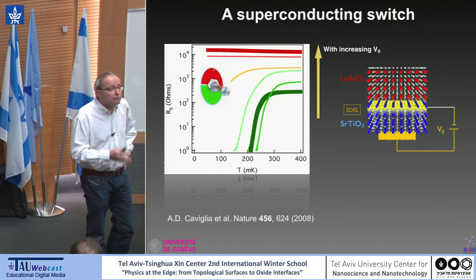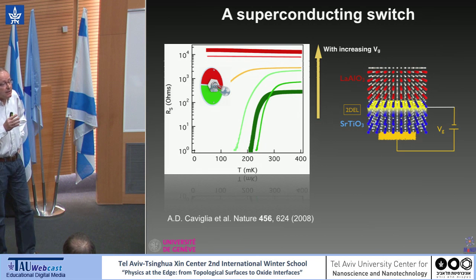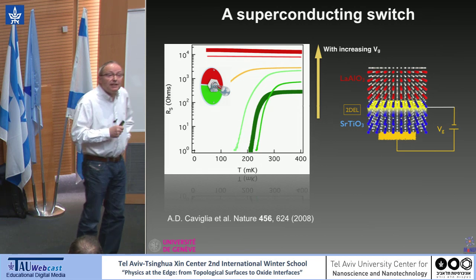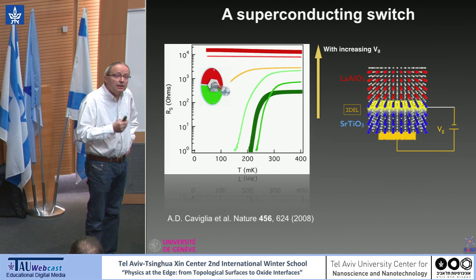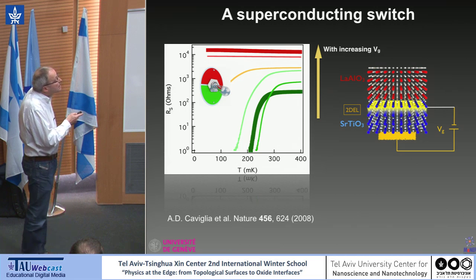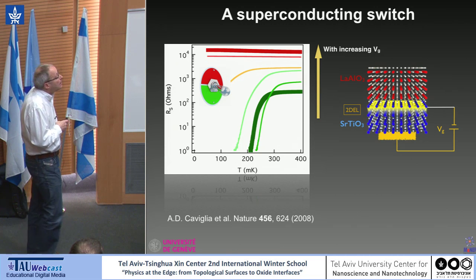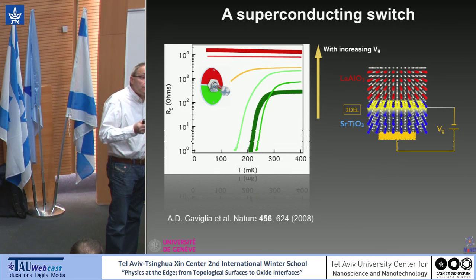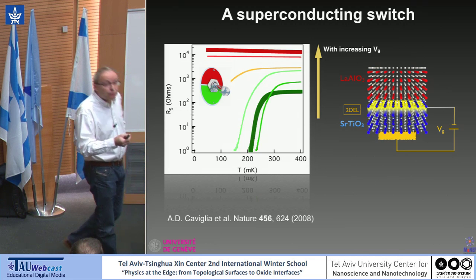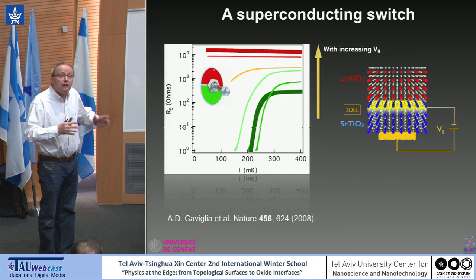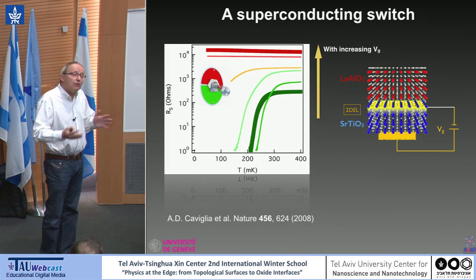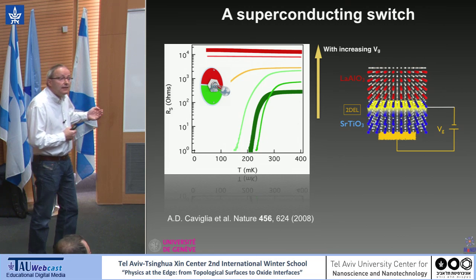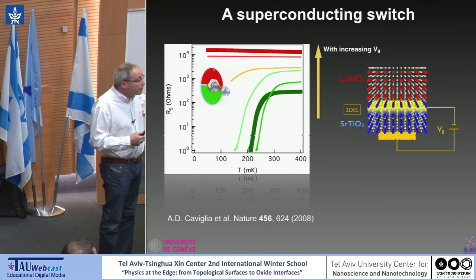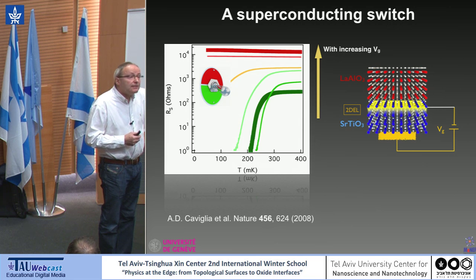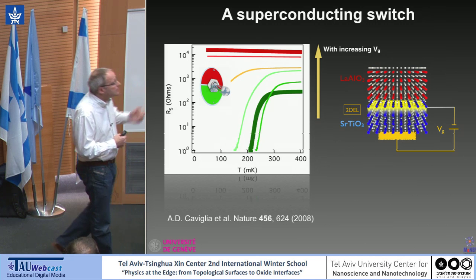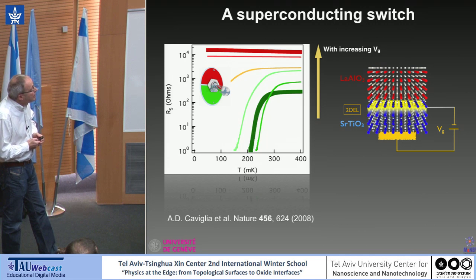And in fact, this is something very difficult. We've been working many, many years on different systems, including high TC, to try using an electric field to control superconductivity. And this is really something quite unique in this system, that you can go back and forth at low T between these two states. Now, you may have seen recent work on cuprates and strontium titanate using the ionic liquid technique, which allows a huge amount of carriers to be induced or removed. This EDLT technique indeed allows on-off switching of superconductivity. The difference is that to change the applied gate, you have to go back to room temperature, because you have to be above the freezing temperature of your ionic liquid. So this is a beautiful switch.